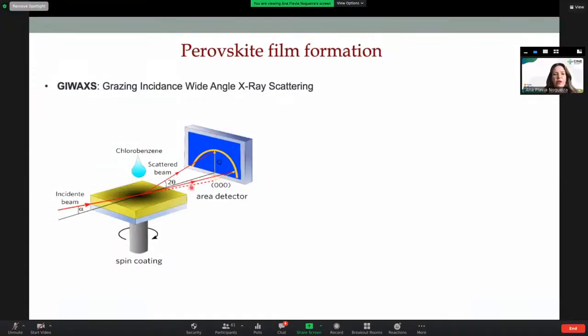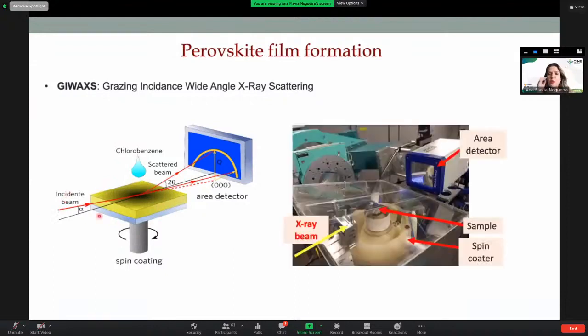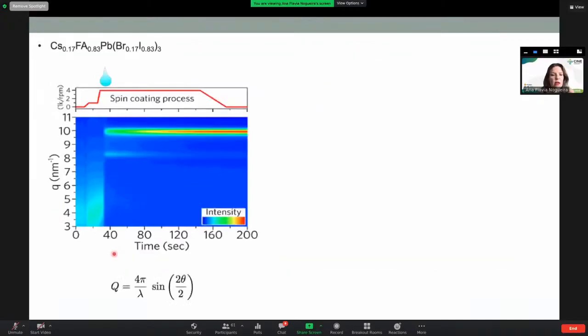So we have your sample here. This is the incident beam. We brought the spin coater from the lab, and we put this spin coater in the beamline. You can see here the X-ray comes from this side. This is our spin coater. That's the area detector. So this is the signal that you can have, the diffraction rings from this film. The signal is related to Q, but if you remember, Q is also related to theta. So this is an example of the data that you can get from the synchrotron.